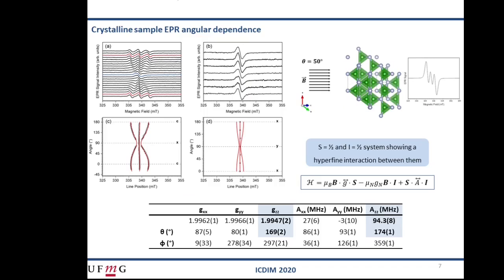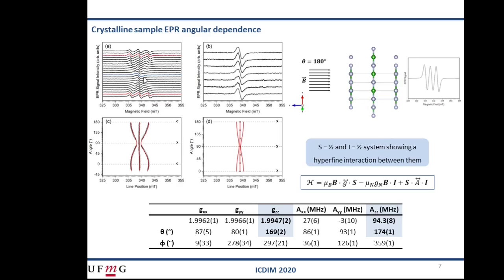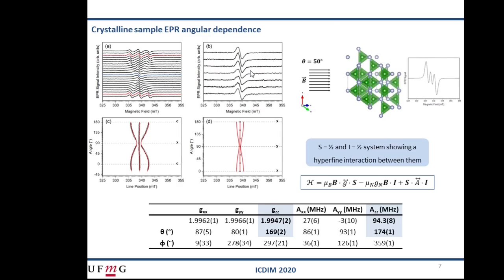Let's begin with the EPR spectrum of the crystalline sample. It is formed by three lines here when the magnetic field is applied along the C direction, and these lines get closer as the magnetic field moves away from the C axis. When the magnetic field is applied always parallel to the hexagonal layers, here in this figure, the EPR spectrum always exhibits a single line.